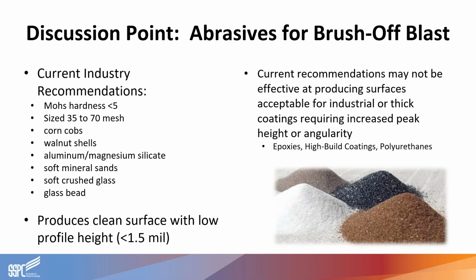Within SSPC SP16, and also within D6386 and D7803, there are recommendations for organic or soft abrasives that can be used to minimize damage to the galvanized surface. These typically are organic media or media that have a Mohs hardness value less than 5, and you may consider finer mesh sizes as well. Organic media such as corn cobs and walnut shells, but we've also seen crushed glass makes that recommendation list as well. These recommendations can certainly be suitable for coatings that require a clean, but maybe only lightly roughened surface.